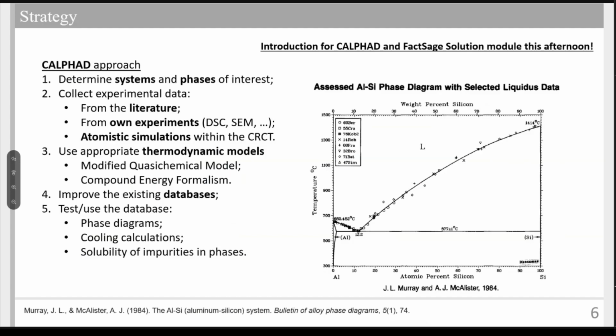The CALPHAD approach, if I summarize it really quickly: we have to determine systems and phases of interest. This afternoon, we'll be looking at one particular simple system, the aluminum silicon phase diagram. From there, we need to collect data from the literature. If such data is not available, we can make our own experiments. We can also use, in our case at the CRCT, atomistic simulations, like we've seen before. After that, we need to choose appropriate thermodynamic models, and one that we developed here at the CRCT is the modified quasi-chemical model. After that, we can improve the existing database, with the goal to test and use the database to make phase diagram calculations and to explore the solubility of impurities in phases.